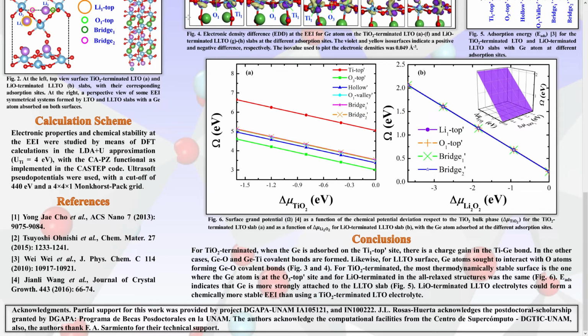Conclusions. For the titanium dioxide termination, when the germanium is adsorbed on the titanium top site, there is a charge gain in the titanium-germanium bond. In the other cases, germanium-oxygen and germanium-titanium covalent bonds are formed. Likewise, for the lithium oxide termination, germanium atoms sought to interact with the oxygen atoms, forming germanium-oxygen covalent bonds. Figure 3 and Figure 4.